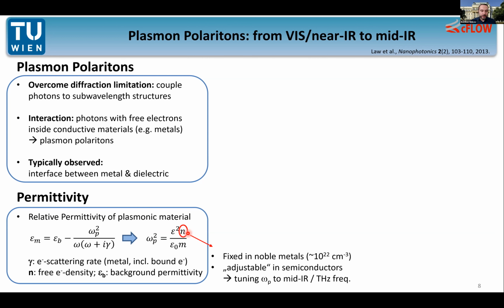So basically, if you look at, for example, noble metals, which have been used in the beginning and still are very often used in the visible and near-infrared spectral range for plasmonics, we see that we have a fixed density of free carriers, typically on the order of 10 to the 22 per cubic centimeter. This also means that the plasma frequency has a more or less fixed value in those metals, and therefore the permittivity is also fixed.